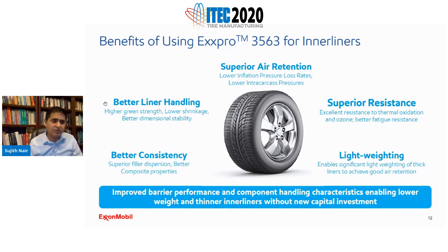Some of the other advantages of Exxpro also is better liner handling. So it's got much better green strength, uncured strength. It's got lower shrinkage, and so better dimensional stability. And then one of the final points is that Exxpro has a very good affinity towards carbon black. And because of this, you get much better dispersion of black in Exxpro, which we will also show you in the forthcoming slides.